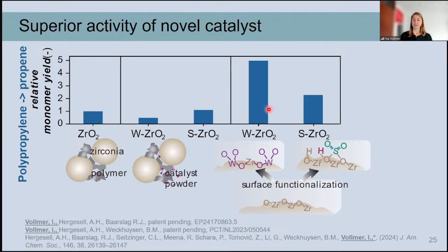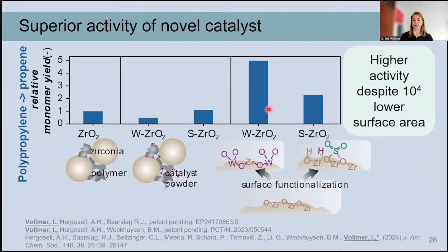And to the heterogeneous catalysis world, this seems maybe a little bit surprising because usually we try to increase the surface area of the catalyst as much as possible. And in this case, we actually have a four orders of magnitude lower surface area of these functionalized grinding spheres compared to the powder. And still the powder is not active, while the surface functionalized grinding spheres actually are. And this really has to do with the improved contact because the catalyst is right where the energy impact into the system is the highest, and also where the polymer experiences the force.